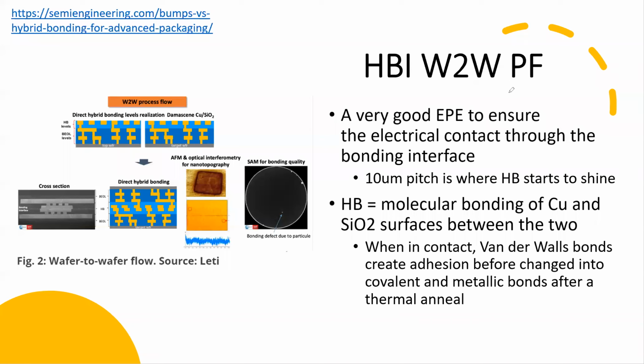If you look at the flow-wise, this is the process flow, wafer to wafer. Then this is what Leti shows, the wafer to wafer flow. When you align them together, you need a very good edge placement, very small edge placement area, right? You align them properly. So it's not too hard, okay? And then the 10 micron pitch is where the hybrid bonding starts to shine. And actually, the hybrid bonding, as I explained, is a molecular bonding of the copper and SiO2 surfaces between the top and bottom wafers. This is direct bonding, direct hybrid bonding. Before they bond it, you make sure it's super clean. And when you make contact, the wafers bond, right?